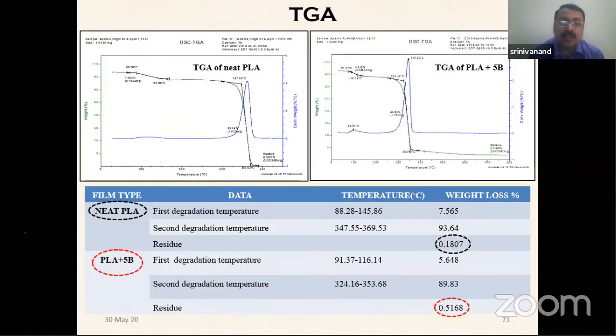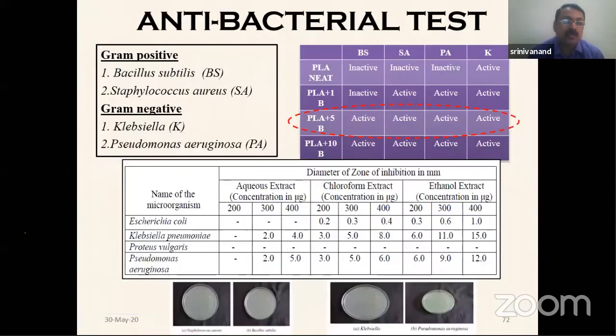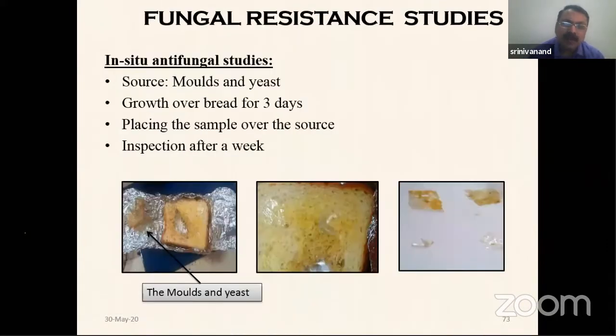And its thermal stability is also found to be high. Though the initial degradation temperature is low for the biocide loaded system, the high temperature resistance is found to be higher in the case of PLA with the 5% biocide loaded system. Similarly, we did the antibacterial study, and we were able to see our films are very active against gram positive and gram negative species. We did the fungal studies.